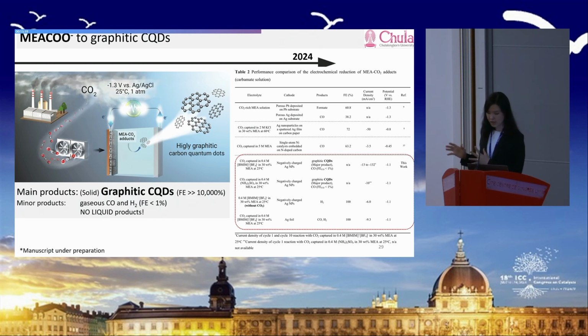And if you look in the literature, there are people trying to do direct conversion of MEA-CO2 as well. We can get CO or formate depending on the electrodes that you use, and the electrolyte is usually CO2 in MEA with some salt. But in our particular system, with our negatively charged silver, there's a lot of graphitic carbon quantum dot formation from this reaction. Again, I can't calculate the Faradaic efficiency. I can, but it gives me an unrealistic number, so it's kind of proof that it's probably not the electrochemical pathway. We did have a small amount of gaseous product like CO and hydrogen, but with Faradaic efficiency less than 1%. There's no liquid product, as we confirmed from NMR.